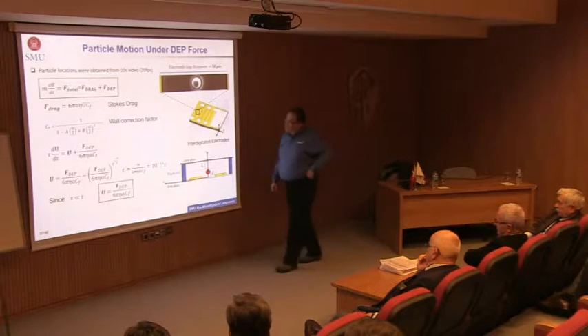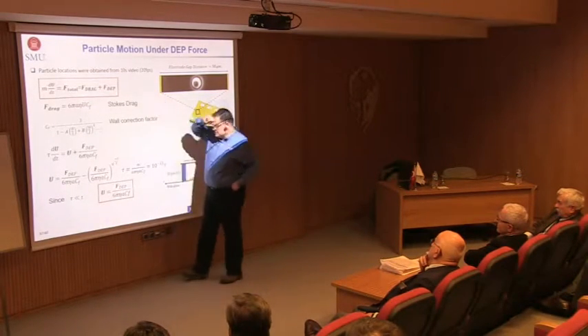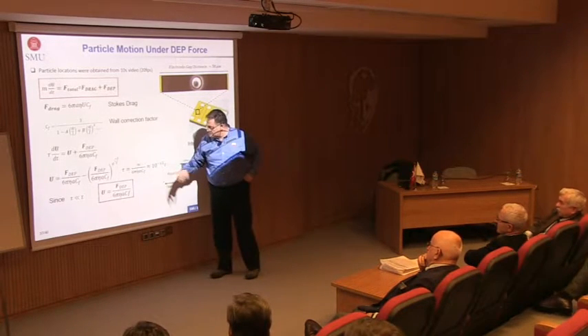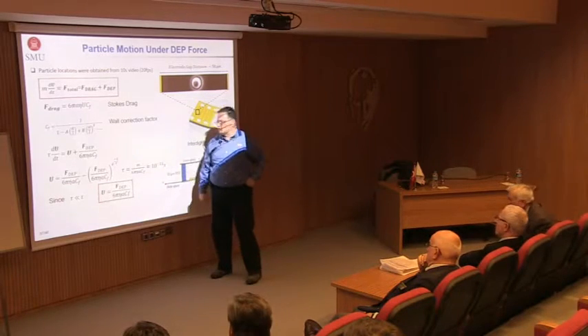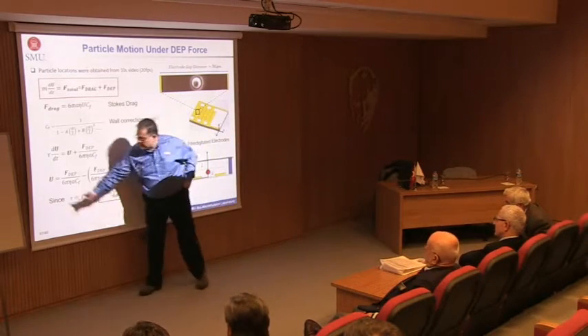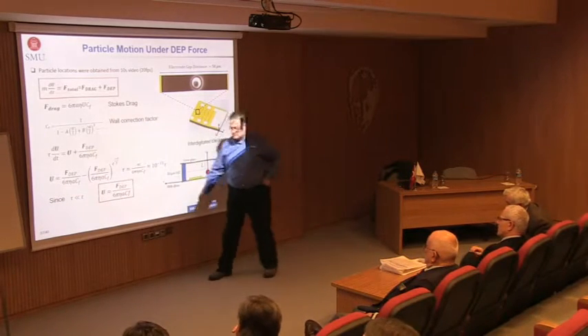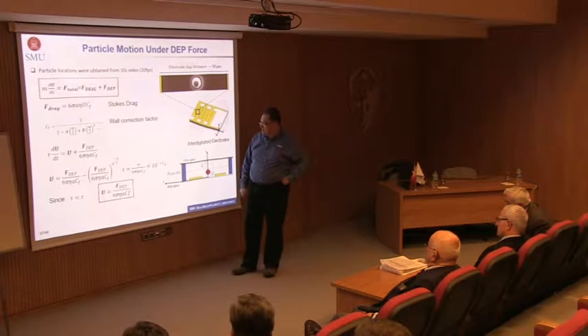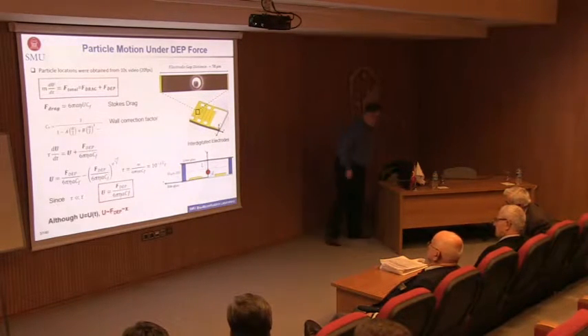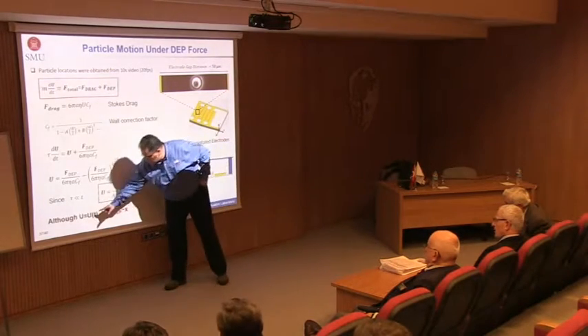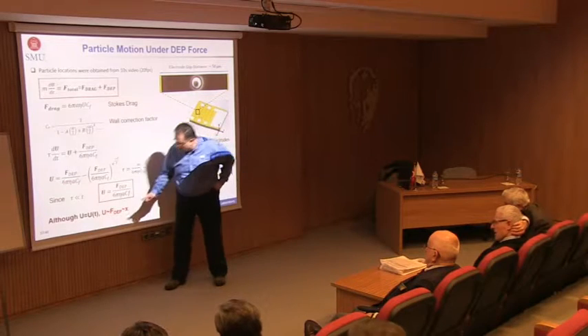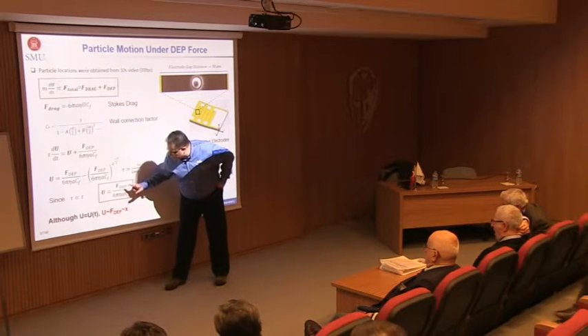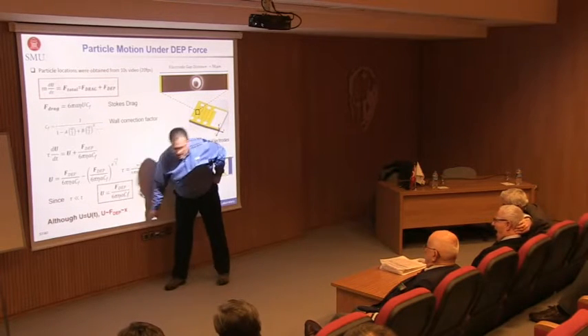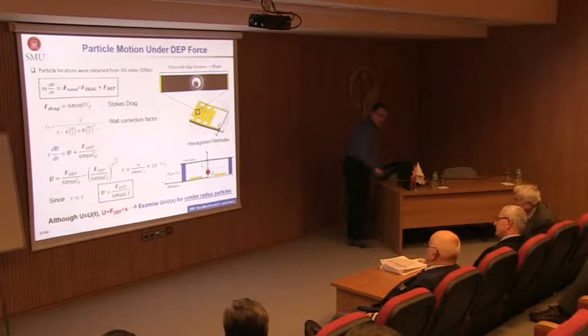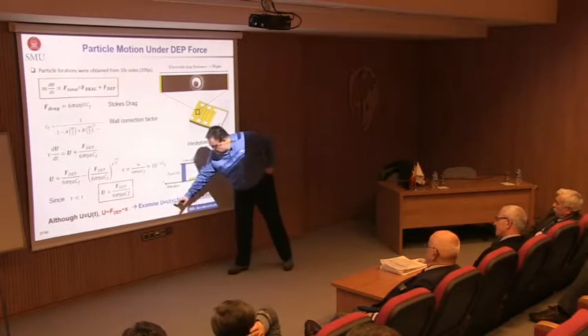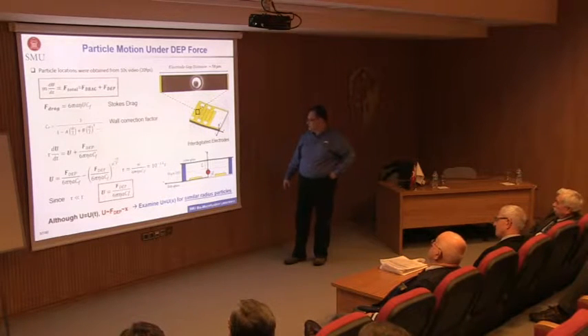So what we do here is we take the motion of the particles for 20 frames per second video. 20 frames per second is too slow to actually understand acceleration of the particle. So you expect that the velocity is balanced with the dielectrophoretic force. So it's almost like a quasi-steady response. Now, the key thing that I would like to show you here is that although the velocity is a function of time, because the particle is moving, because it is proportional to the DEP force, which changes with space, you can actually see your results as the velocity changing as a function of space. This is only true if you have identical or similar radius particles.